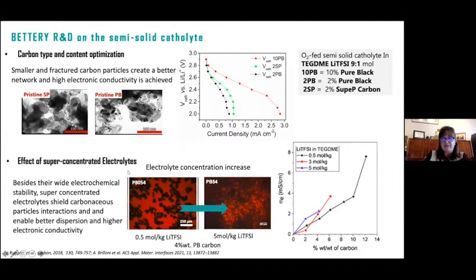This new class of electrolytes is very promising for its electrochemical stability, but we also demonstrated an additional feature. Besides the wide electrochemical stability, super concentrated electrolytes, by their ionic environment, can shield carbonaceous particle interaction and enable a better dispersion and a higher electronic conductivity, as you can see here. So even with this approach, you can improve the conductivity of the electrode and therefore achieve lower overvoltage.